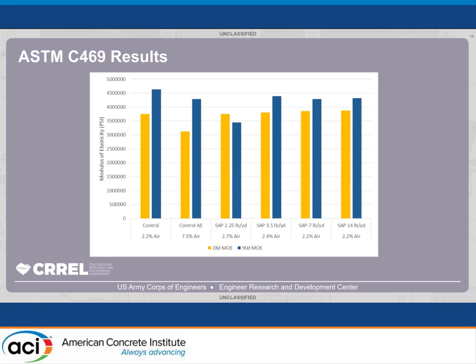These are our modulus of elasticity results. Not too much to report here, but again, our values at 28 days and 90 days were comparable to the control, and more than the control at 7 days in most cases. This is a test we run pretty standardly, and there's not always a lot from it, but these were acceptable results to us.